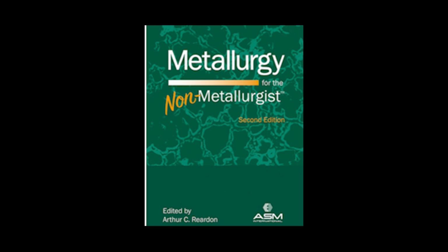And that rapid cooling does what? It traps the carbon atoms and forces the austenite to transform into a very hard, strong, but often quite brittle structure called martensite. Brittle isn't always good, though. Usually not. So after hardening, you almost always do tempering. This involves reheating the hardened steel to a lower temperature, holding it for a bit, and then cooling it. This reduces the brittleness, makes it tougher, while still keeping a lot of the hardness and strength gained from quenching. It's a balancing act.